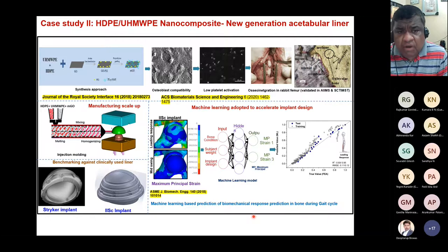their viscosity is lowered. And further, we have added a very small amount of graphene oxide, but graphene oxide dispersion in a polymer blend is not an easy task. So we have done some polyethylene grafting on the graphene oxide, and that allowed us to disperse this graphene oxide in this polymer blend. And now these materials have good osteoblast compatibility as well as blood compatibility, and we have done osseointegration in the rabbit model.